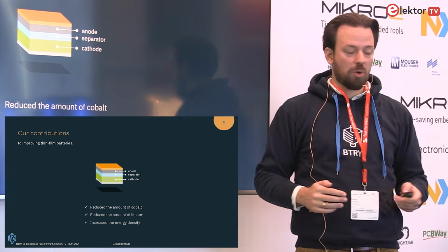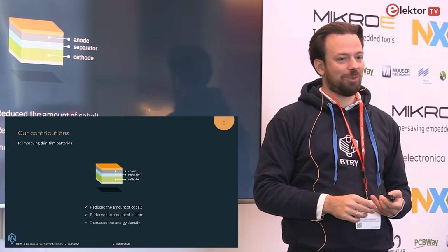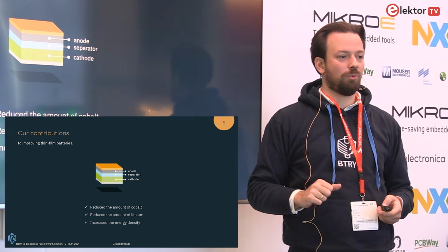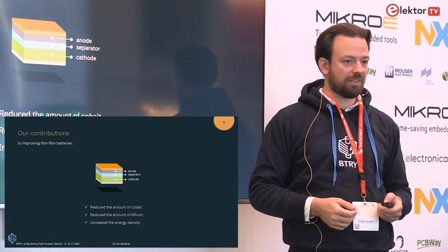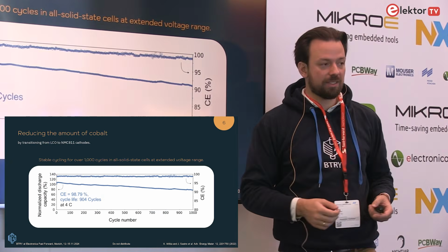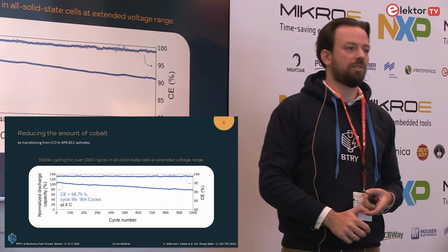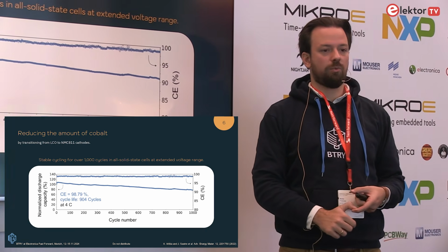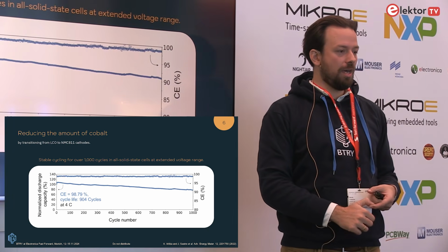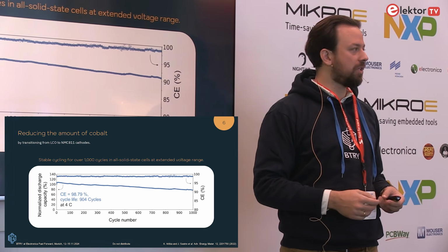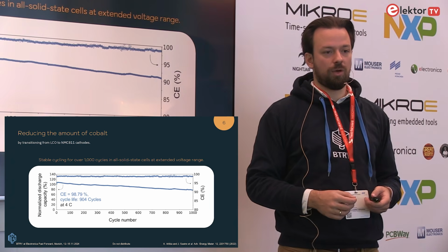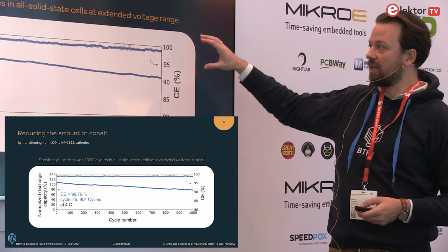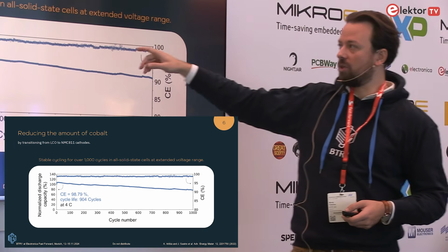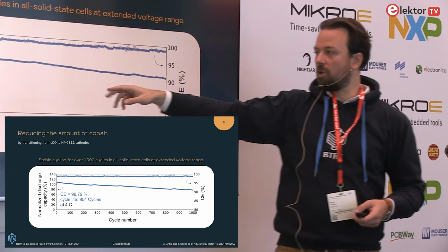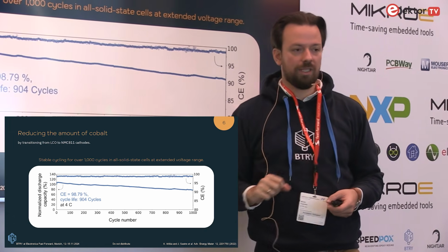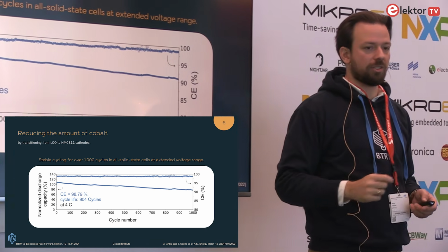That's it. Now, what have we contributed to thin film batteries? I will quickly share what work we have done before incorporating the startup. One is we have worked on the cathode. Typically, thin film batteries are made with lithium cobalt oxide cathodes. We have worked on changing this to use NMC 811 cathodes in our films. And here you see the cycling performance of one of these cells, which in this case has a cycle life of about 900 cycles at 4C, so relatively quick charging and discharging.